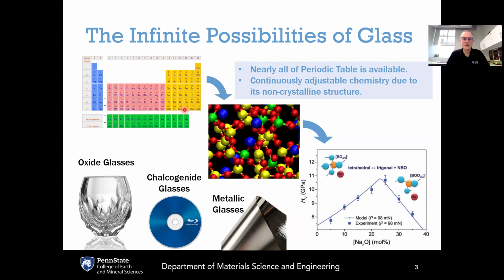And another byproduct of the non-crystalline structure of the glass is that the chemistry is continuously adjustable. That means you don't have to satisfy certain proportions of certain elements to each other because you can continuously adjust that chemistry of the liquid state and then take that liquid state and quench it into the glass.